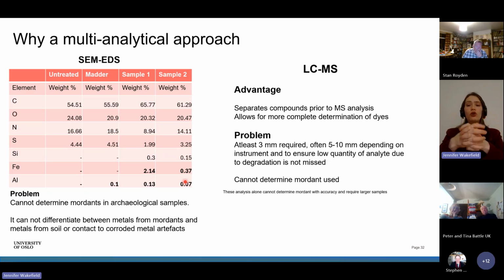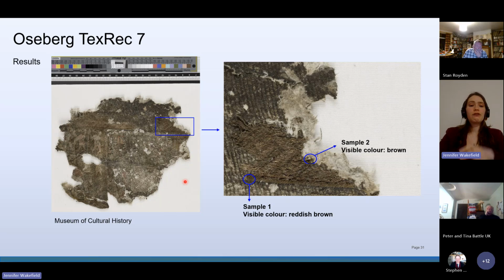In some cases, you can also have MSMS, and that's where you identify the mass of the compound, but you then also break down the compound, which gives you a fingerprint of the different masses that make up fragments of that compound. So you can then match it to a database. If you create a database of all the different dyes out there, you can then match it. So you have a third confirmation of whether or not it is your dye. But this requires a larger sample size than what would be really suitable for some of the ones with these figure motifs. You couldn't take samples that big from these figures.